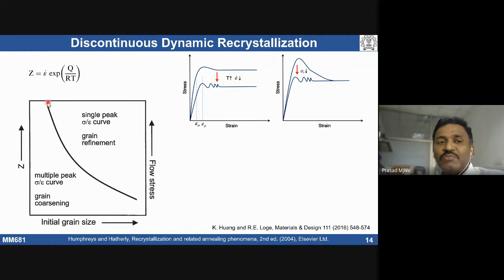Typically there is a boundary established for a given material. So what does it mean? At a given initial grain size, higher Z leads to a single peak, lower Z leads to multiple peaks. When I say lower Z, that means lower strain rate or higher temperature. Lower strain rate or higher temperature can lead to multiple peaks. Higher Z can lead to a single peak in a DRX stress strain curve of the material.